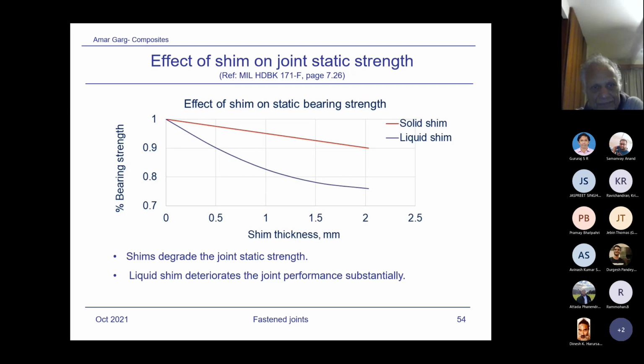As you can see from here, the effect of shim on static bearing strength. You have a solid shim and you have a liquid shim. Liquid shim, when I said elastomeric materials, is moldable, and you can see the degradation. Suppose shim thickness is only 0.5 millimeter, and a 0.5 millimeter thin shim will bring down the bearing strength by 10%.